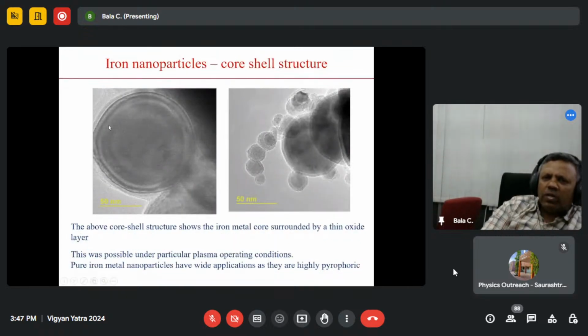and also you can get core-shell particles. You see, you have an iron oxide particle, you have core iron, and you have the oxide layer on the iron, and it's very much seen here. You can see this one. All of them have a different inner core and a different outer shell.